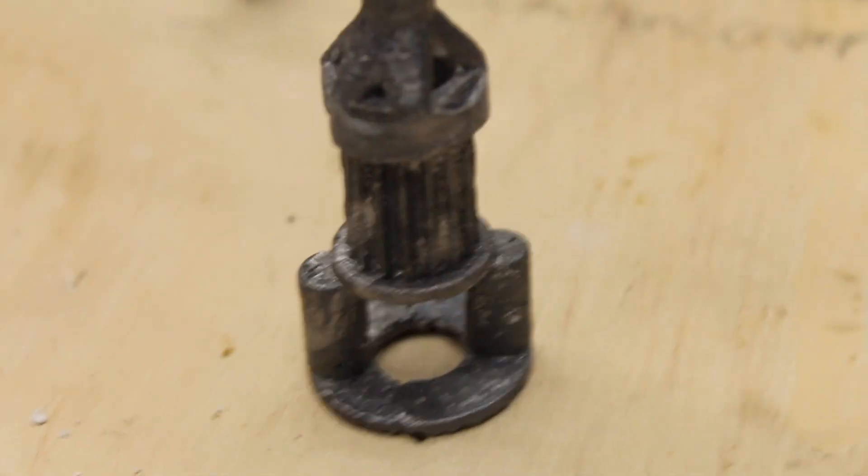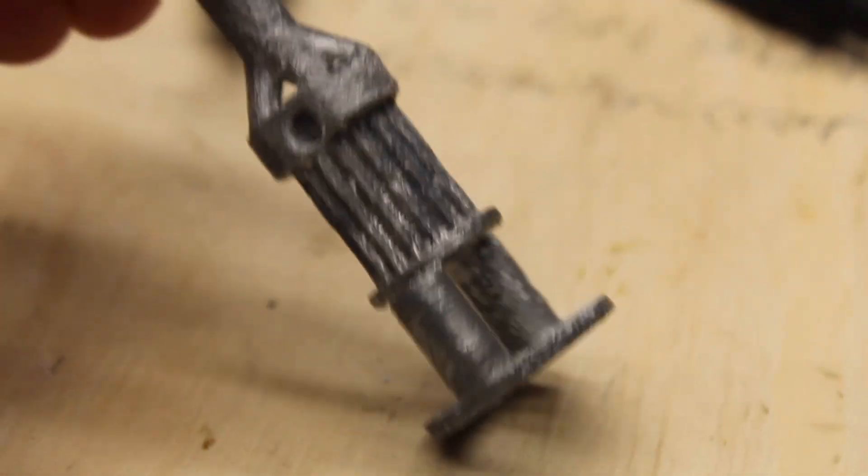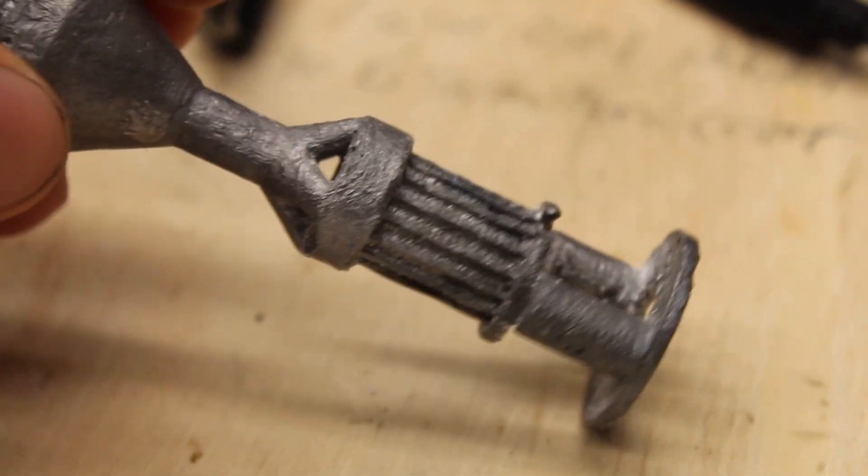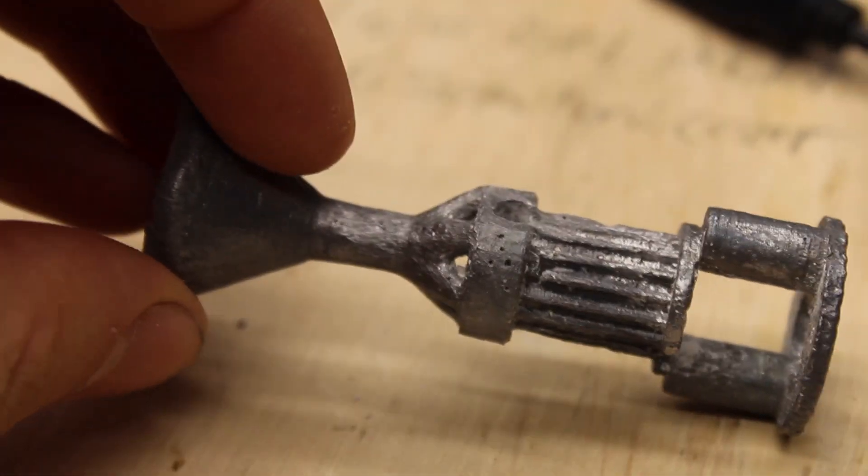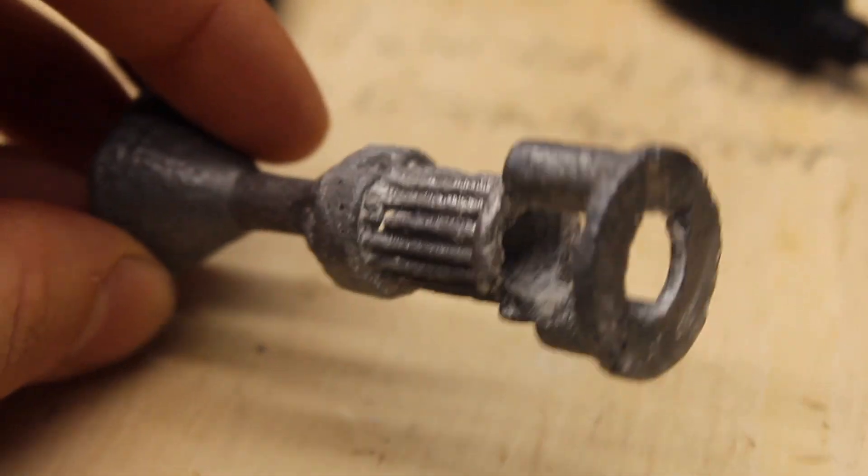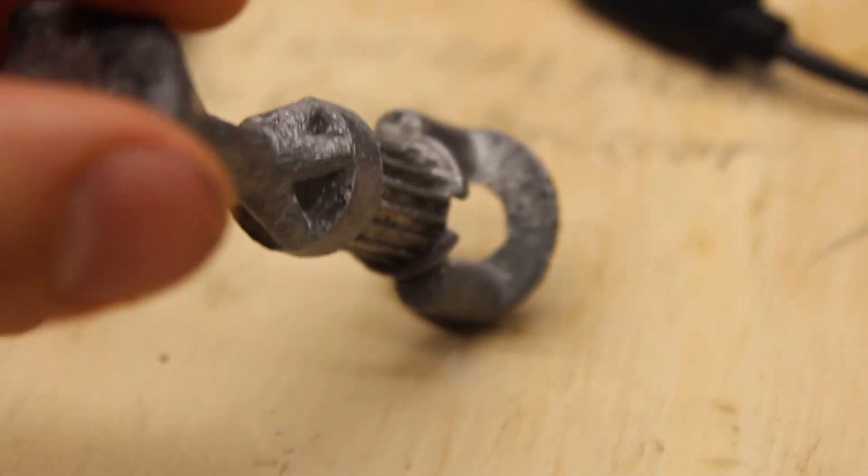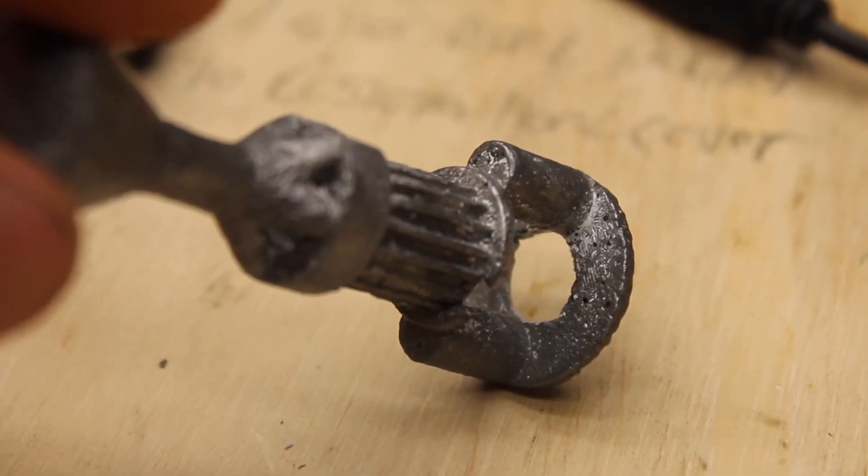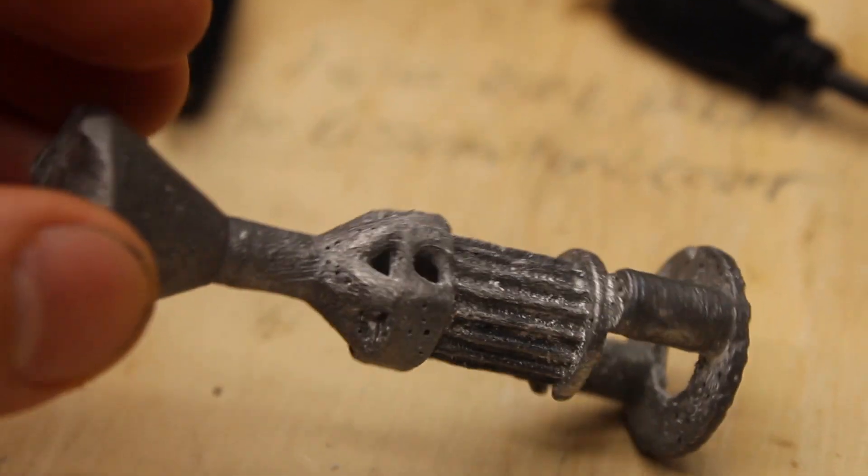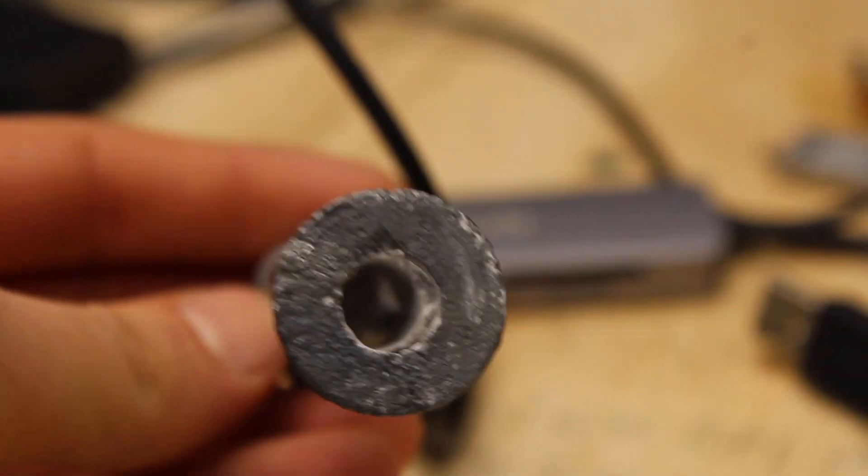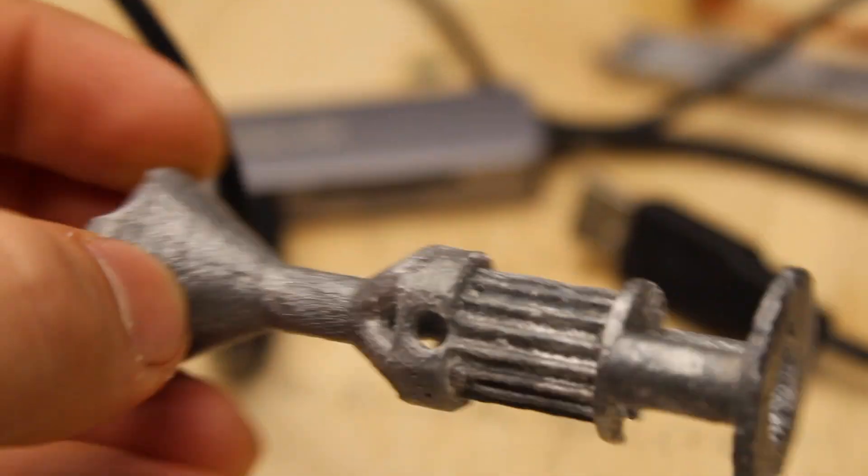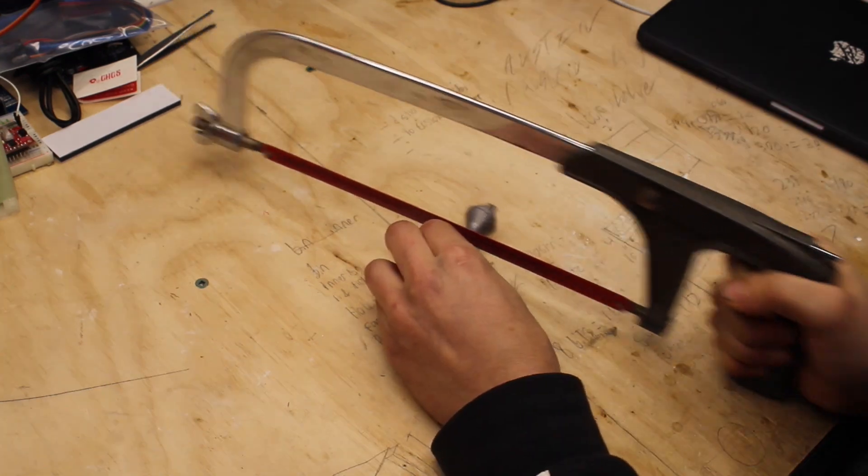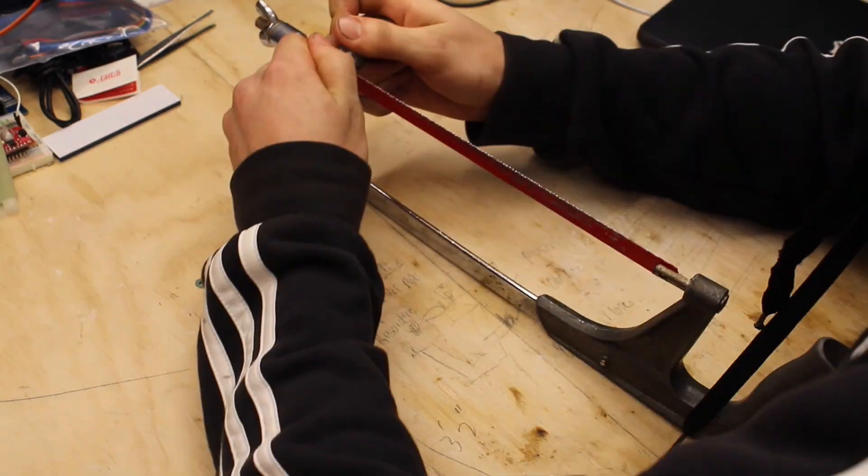So this is the, this was the final product. And you can actually see what the intention was with the molds. And it came out pretty well. I shook it a lot to make sure it filled in all the gaps. And that's why the surface finish is so shit. But, you know, I'm quite happy. There's a lot of bubbles. I definitely should have degassed it. And I'll definitely do that next time. Yeah. If you, it didn't. I'm not exactly sure. But it worked pretty well.